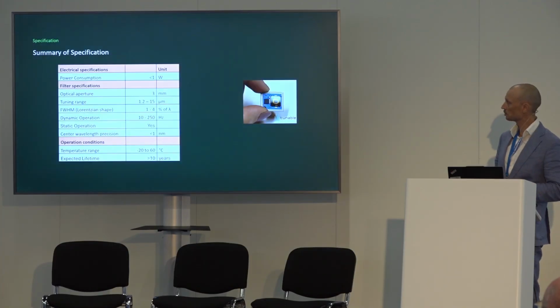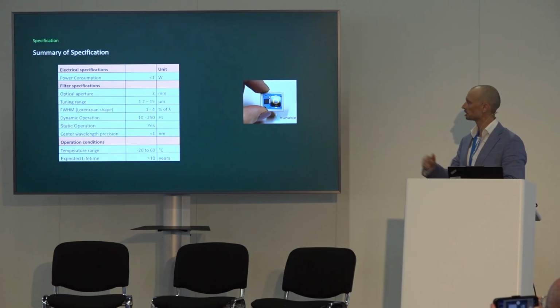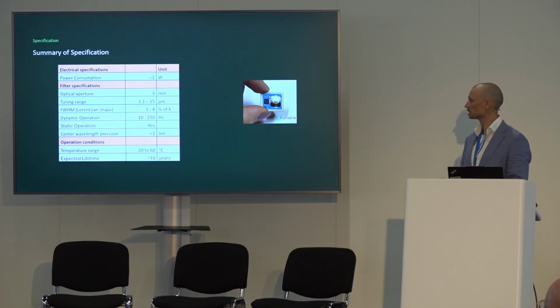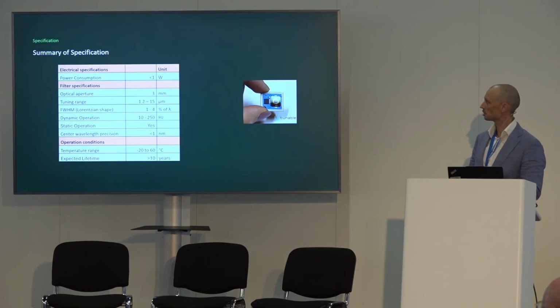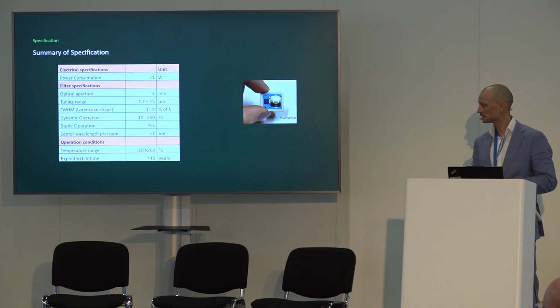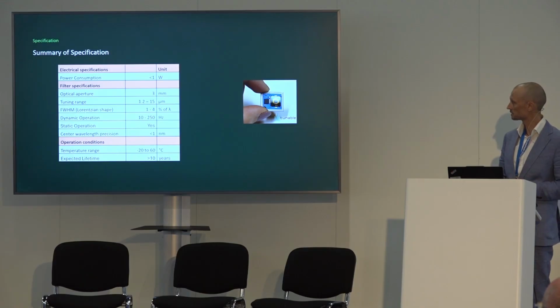So in summary, what that boils down to when it comes to the filter, you see here, we have an optical aperture of 3 millimeters. We work in the range from 1 to 15 microns. Our full width half maximum is pretty wide, from 1 to 4% of the center wavelength. We can operate dynamically with a frequency of up to 250 hertz and statically. Our center wavelength precision is below 1 nanometer. Temperature range from -20 to 60, and lifetime expectancy of above 10 years.